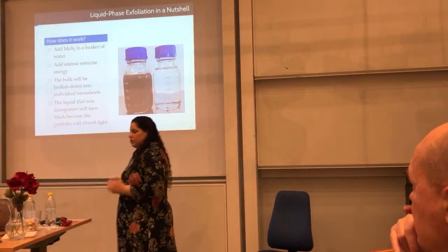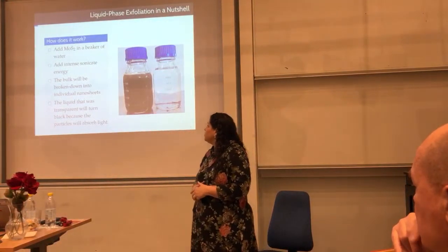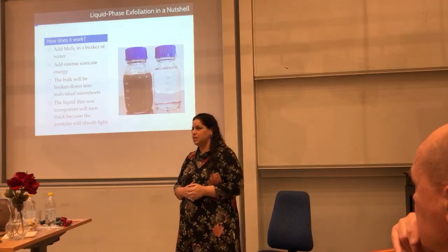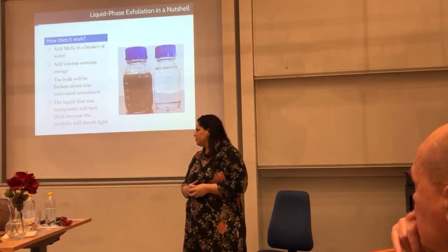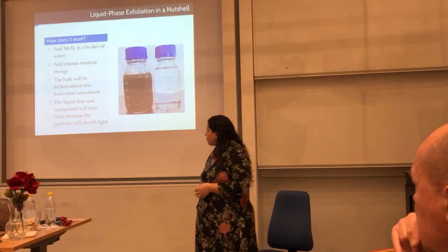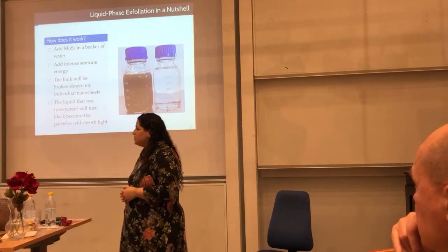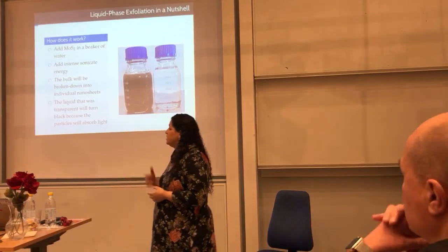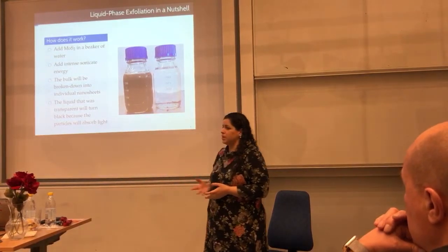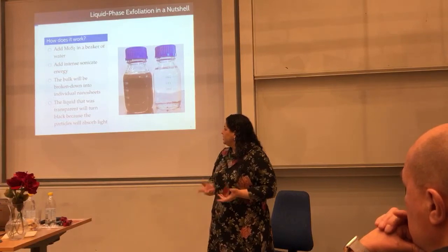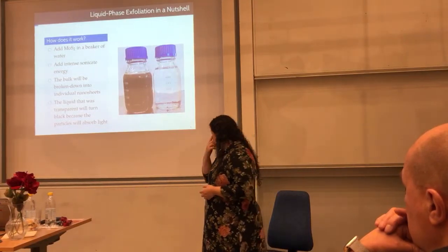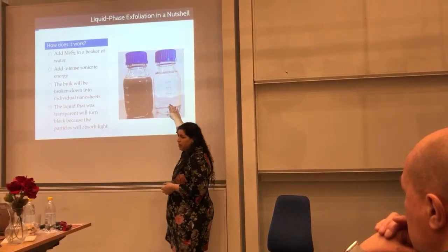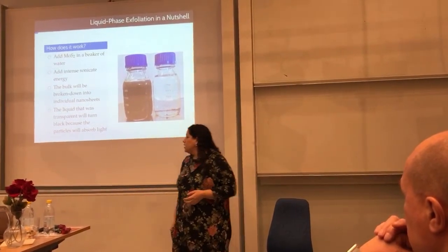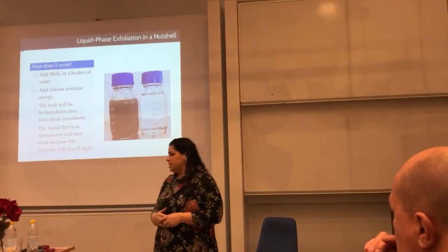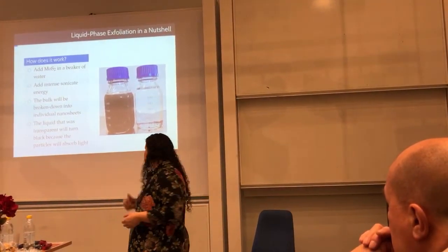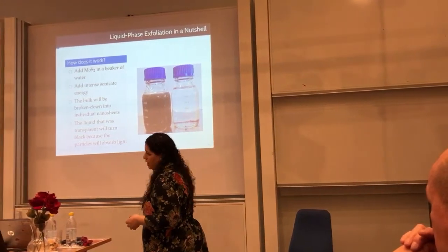Let's see. To start with, I want to give a brief overview of what liquid phase exfoliation is, so anyone could understand. Basically, what you do is that you add the layered material, in this case molybdenum sulfide, into a beaker of water or solvent. You add intense sonication energy, and then this bulk powder that was initially transparent in water will turn black. The reason that it turns black is that the particles will be individualized and they will start to absorb light, and then they are black in dispersion.